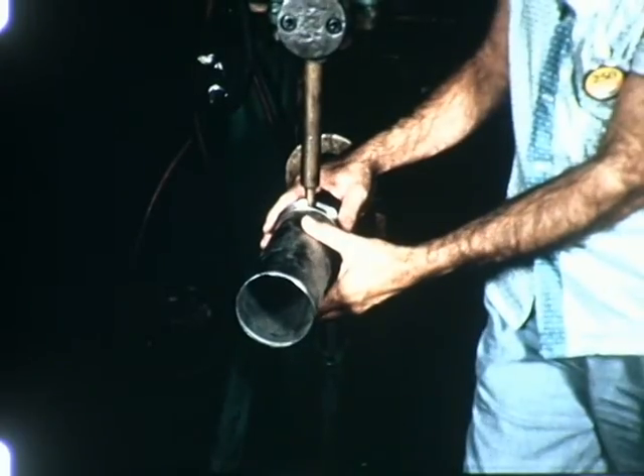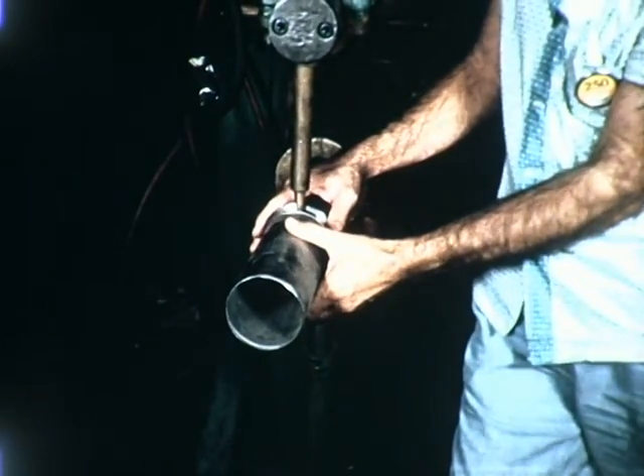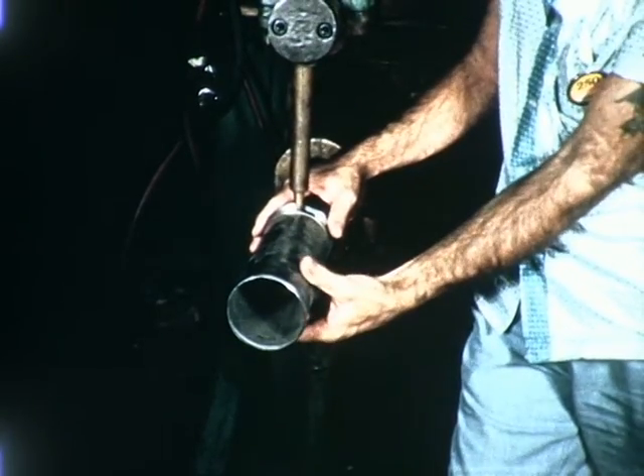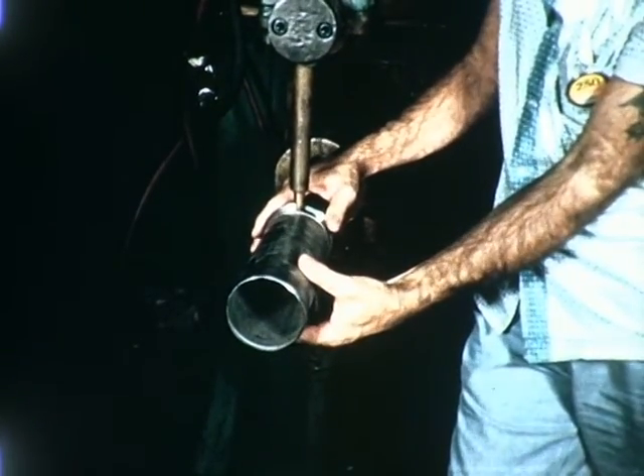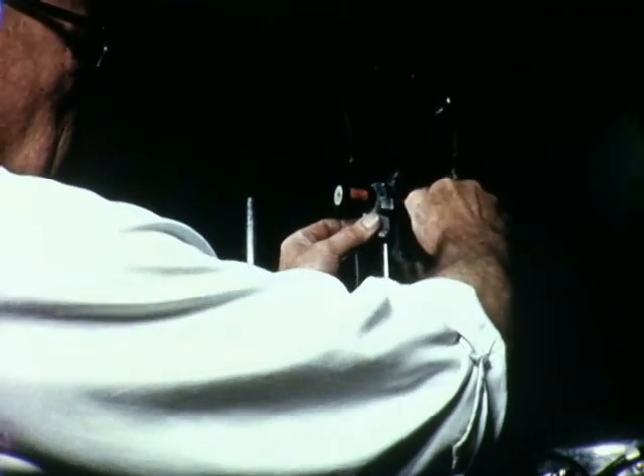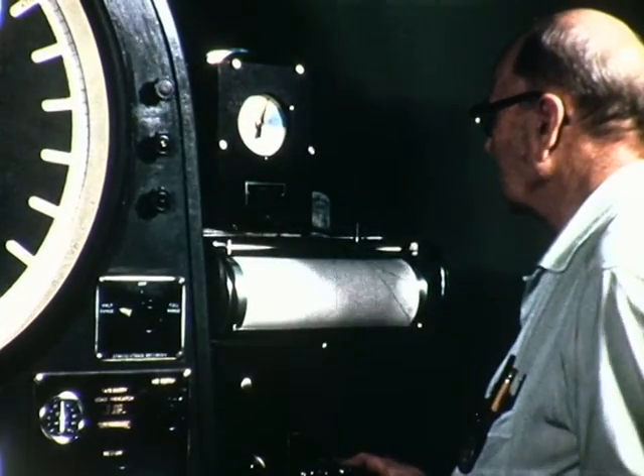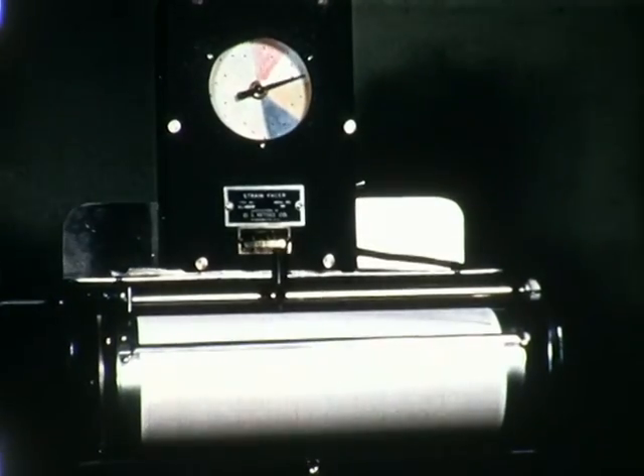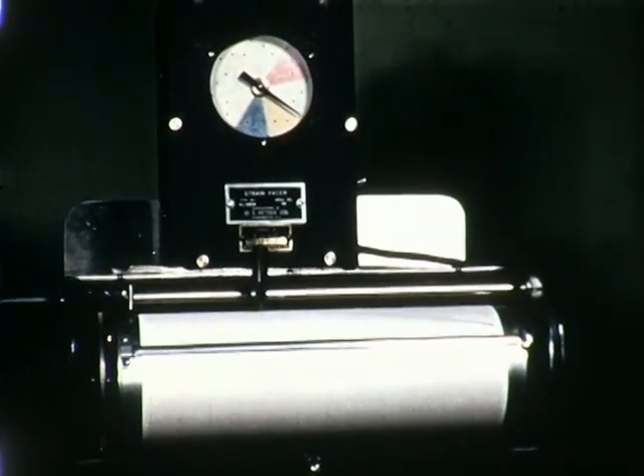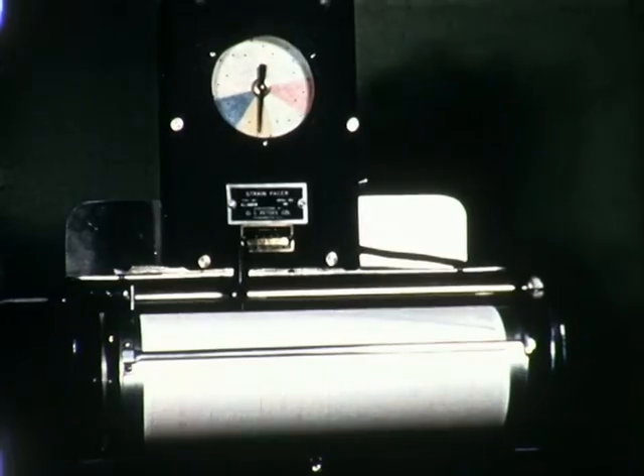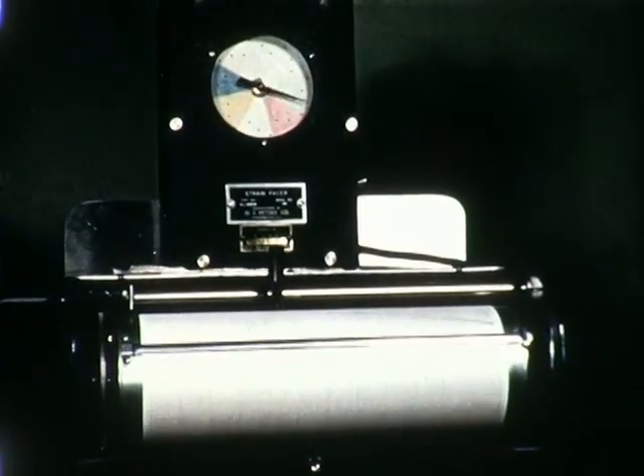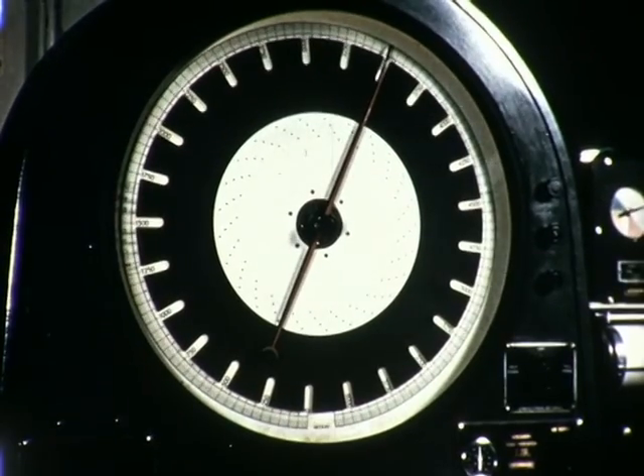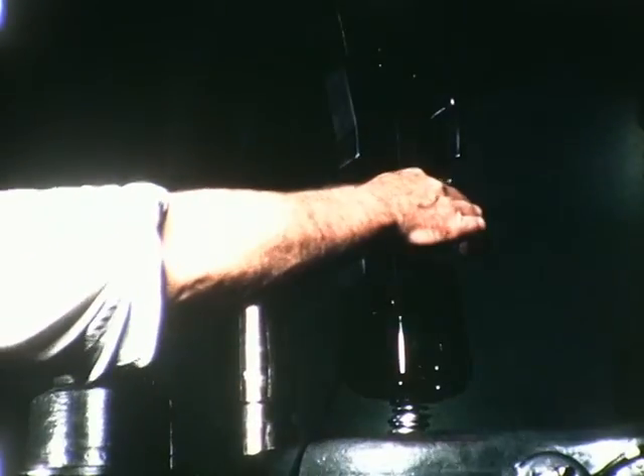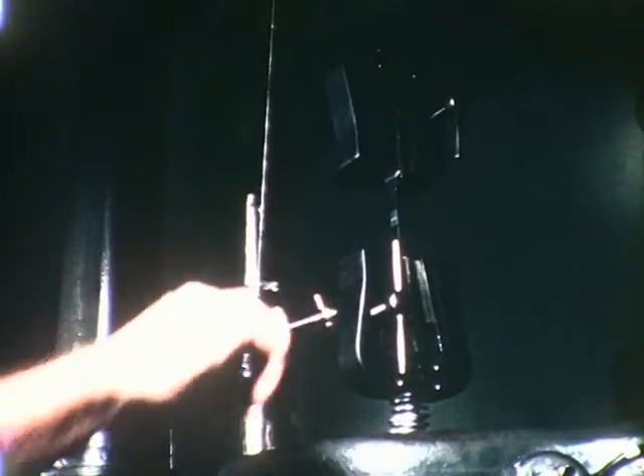Rene 41 is one of the most difficult metals to resistance weld that we have encountered at Ryan. High tip pressure is required. The main problem is the difficulty in achieving acceptable nugget size. Weld samples were prepared for tensile testing. The samples were in two stages of processing, as-welded and annealed. The as-welded sample had a tensile strength of 22,000 pounds per square inch. The annealed sample had a tensile strength of 124,000 pounds per square inch. It's apparent that there is a difference in the weld strength between the as-welded and the annealed condition.